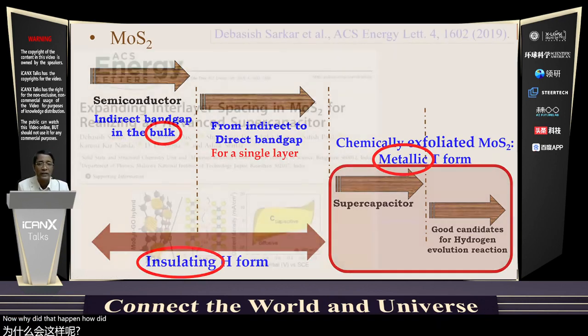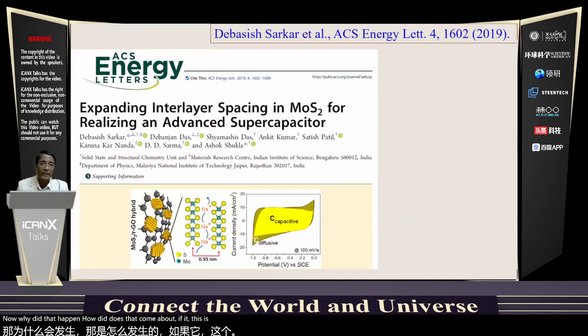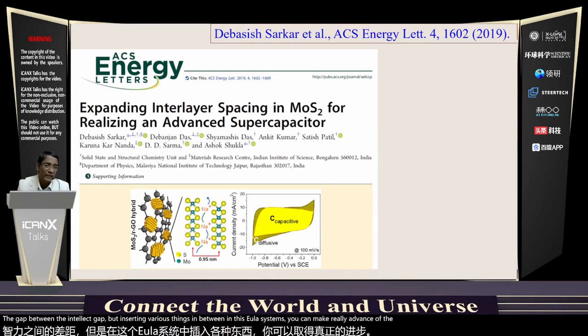How does that come about? In fact, this is one paper that we had ourselves published some time back in ACS Energy Letters, showing that if you take this MoS2 and tune the interlayer gap by inserting various things in between these few layer systems, you can make really advanced supercapacitors with fantastic properties.